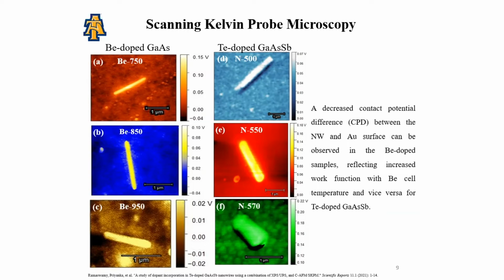From these SKPM surface potential images, a decreased contact potential difference between the nanowire and gold surface can be observed in the beryllium-doped samples, which reflects increased work function with beryllium cell temperature, and vice versa for tellurium-doped gallium arsenide antimonide nanowires. However, as the measurement is carried out at room temperature, the bias voltage, probe tips, and also the presence of adsorbents and surface states in the nanoscale regime have a significant effect on the surface potential measurement. Hence, quantitative analysis was not performed.